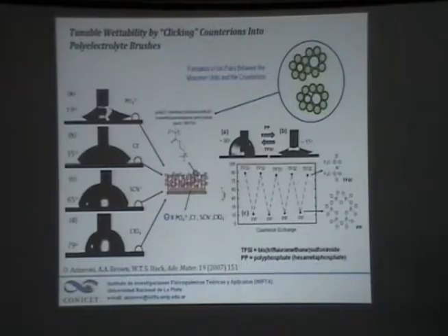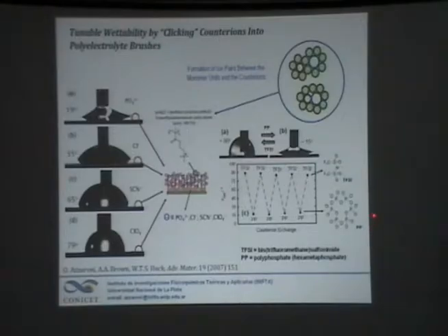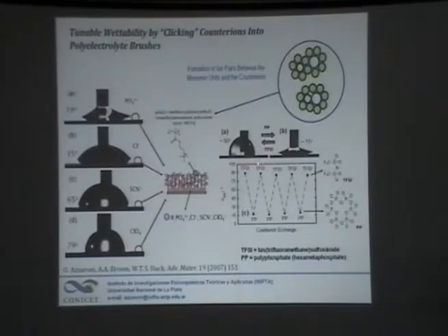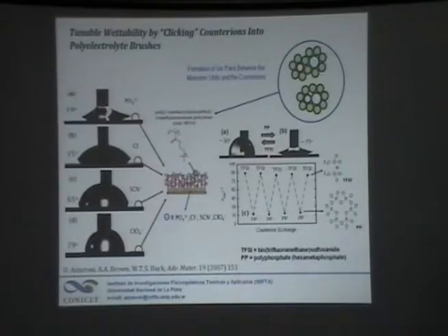You can enhance this further. If you use anions which are perfluorinated, such as TFSI, or anions which are highly hydrophilic like polyphosphate, you can prepare exactly the same polymer brush and by exchanging the counter-ions you can change the surface character in a drastic way — from a very hydrophilic surface to a very hydrophobic surface — in a very simple manner, just by dipping in water and exchanging the counter-ion.